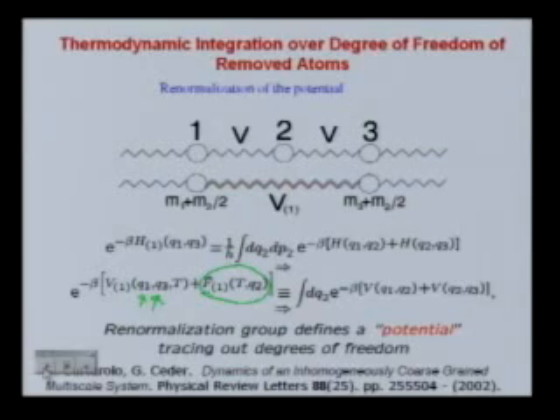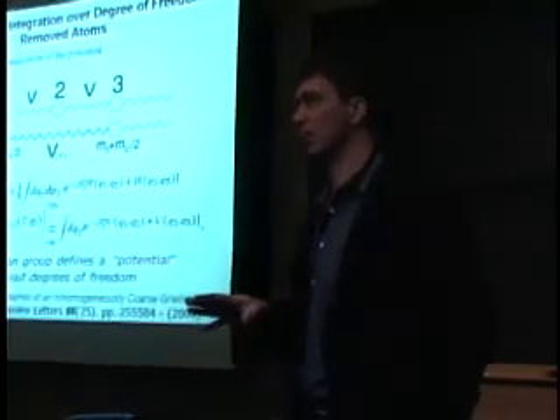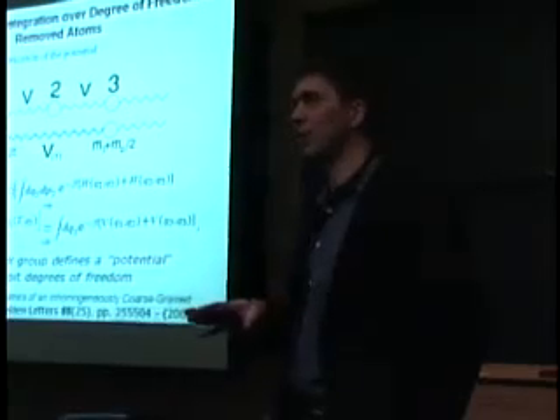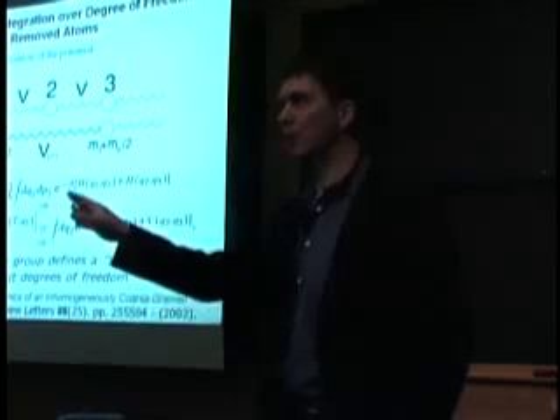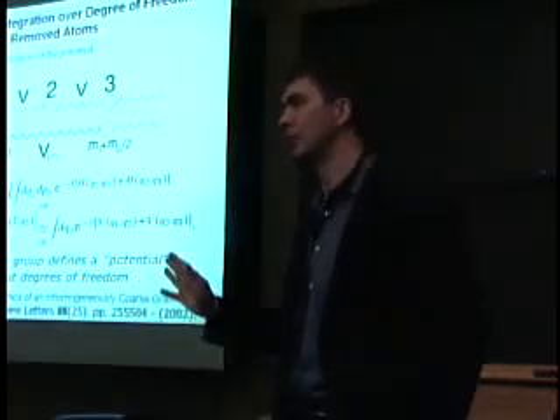That's why, if you look back at the slide where we defined the effective potential between atoms 1 and 3, there's actually a potential, and then there's a part that doesn't contain the coordinates of 1 and 3. It's essentially the entropy you've lost by removing node 2. You have to keep that entropy in the system if you want to get the total thermodynamic quantities right. This is obvious if you take the complete limit of removing all nodes, or going to one node—then you end up with continuum behavior.